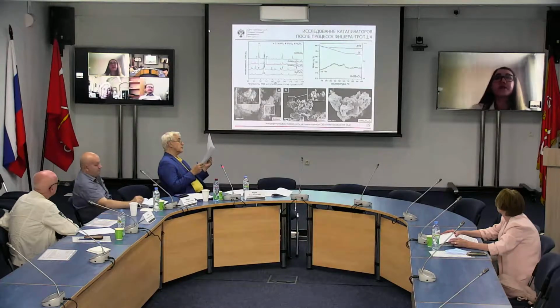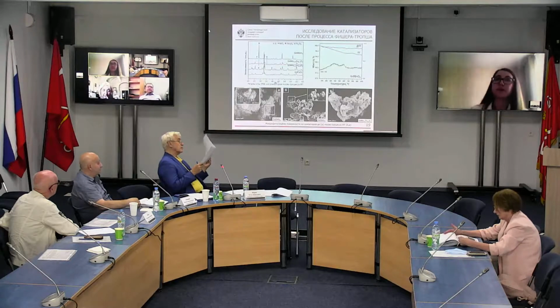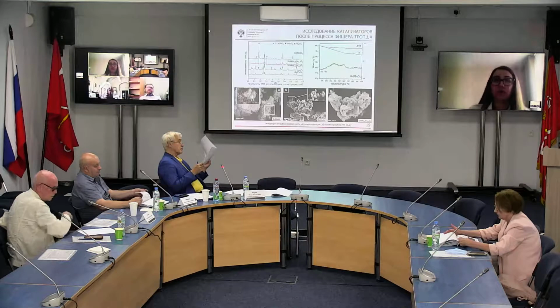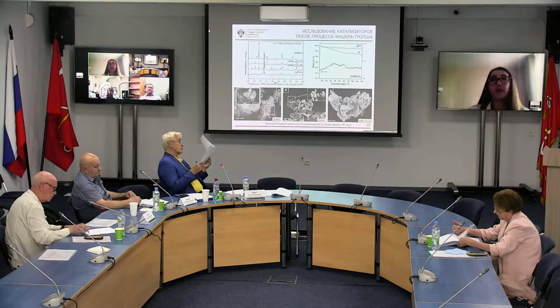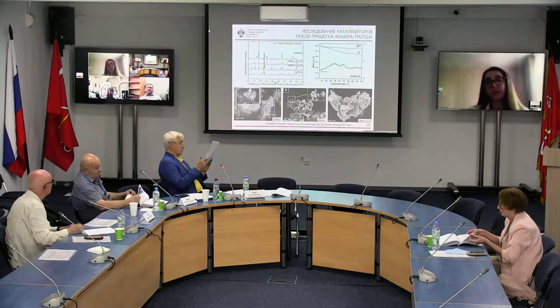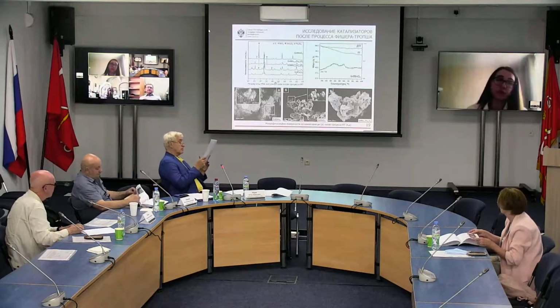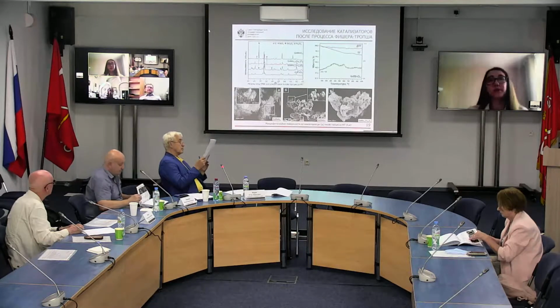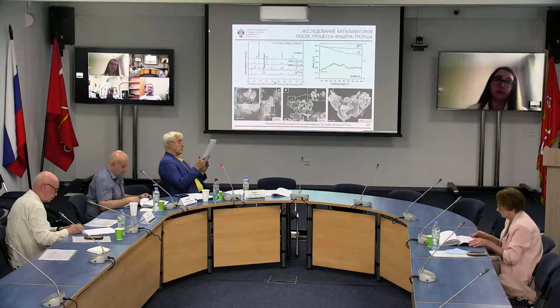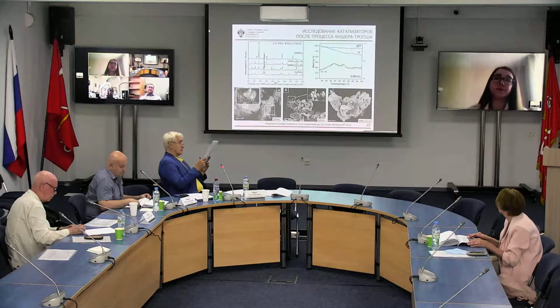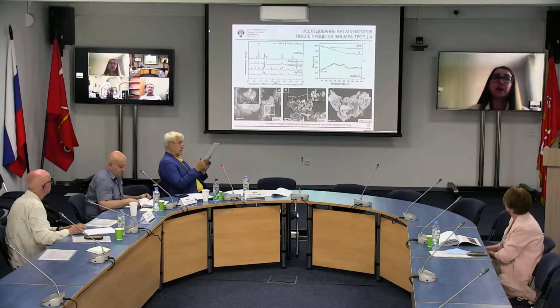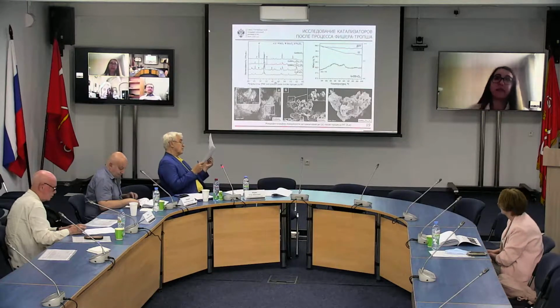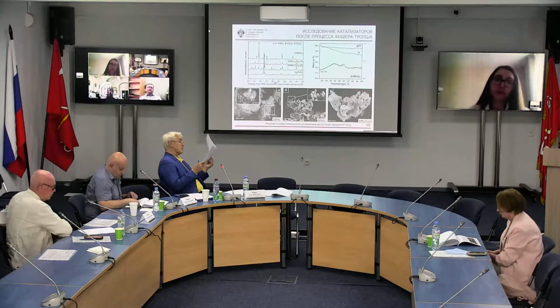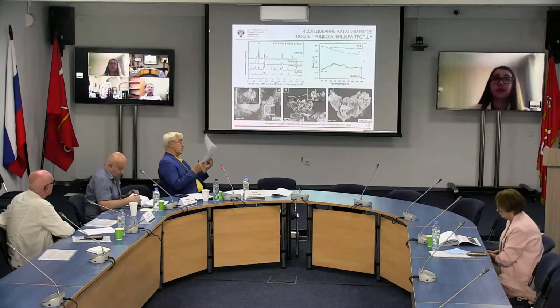And on the slide you also see the results of the phase content study for manganese-containing ferrites after the Fischer-Tropsch process. This data were obtained after 48 hours of testing at temperatures of 250-450 degrees Celsius, and the results show that for gadolinium ferrite we saw no phase content change, and gadolinium manganese iron O3 demonstrates partial destruction of the structure, and we also see diffraction peaks characteristic for gadolinium manganite, gadolinium oxide, and iron oxide Fe2O3. For other substances, we see no change in phase content.